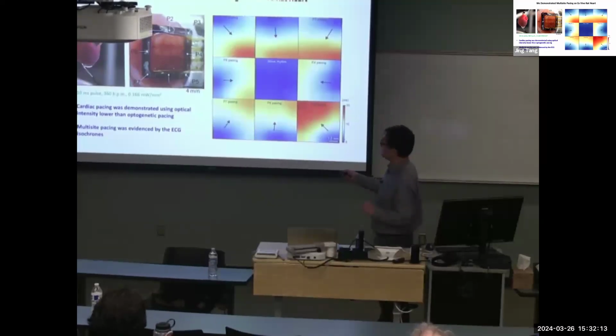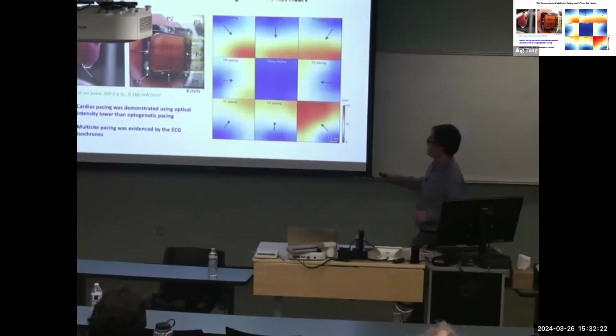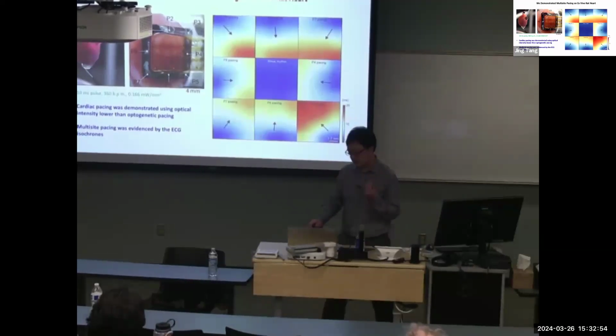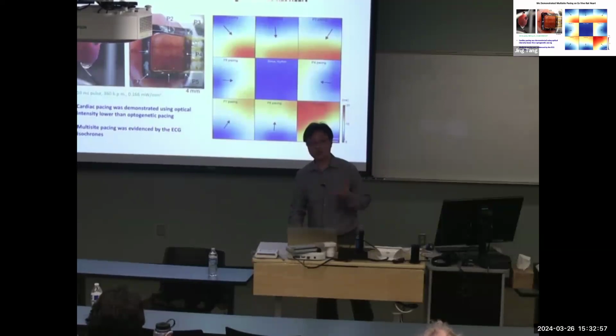This is not random access because the light always hits close to the center of the silicon membrane. This can address the random access, or at least close to that. This is a silicon membrane, but the center is open, where we put a microelectrode array for cardiac mapping. So there are both stimulation and sensing components. You can do photostimulation at different spots, like P1, P2, P3, all the way to P8. What you found from this is the cardiac isochrone mapping. You can see that when you hit light at different locations, it actually gives you a different result, suggesting that there's a need for random access or precision photostimulation.